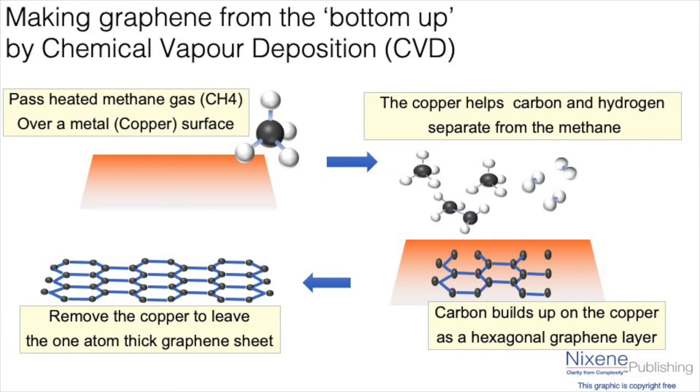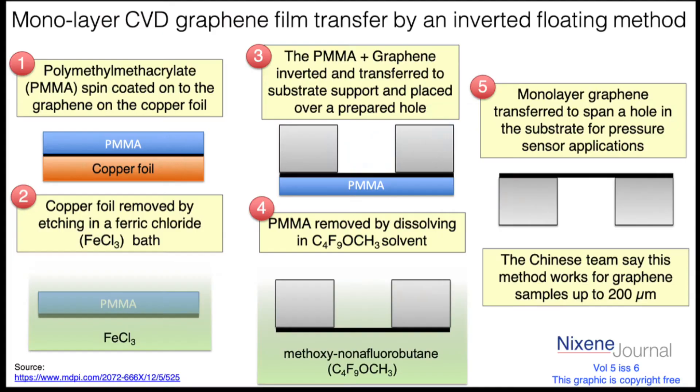So that's how we get a one-atom-thick layer of graphene on the copper. The question is quite well informed — now how do you get the graphene off? You could put some sticky tape on and pull it off, but you might damage it. The other method, used by probably the majority of processes right now, is to dissolve the copper away underneath. They don't always use acid — ferric chloride, which has acidic properties, is used to etch away the copper. You're then left with graphene floating on the surface of liquid, and you bring another surface — maybe plastic — in contact with it and peel it off.